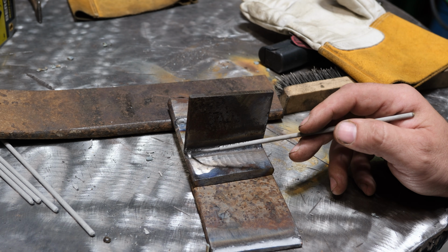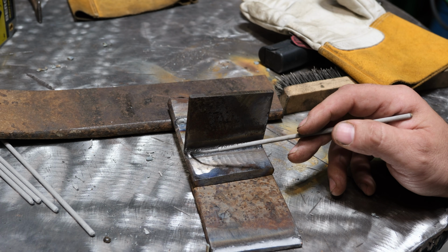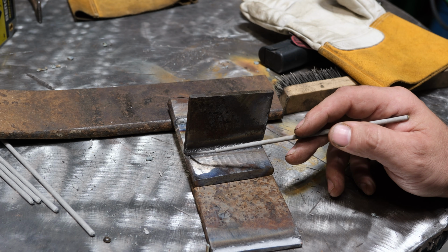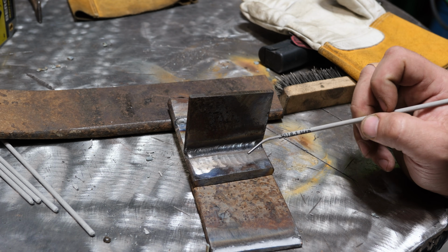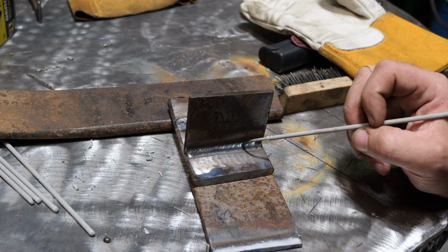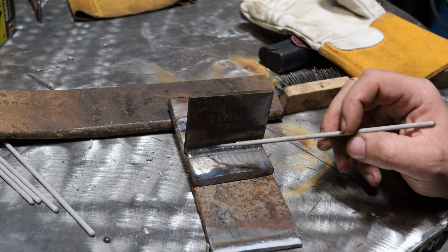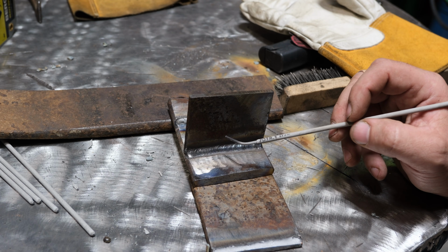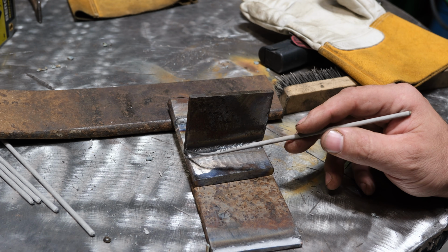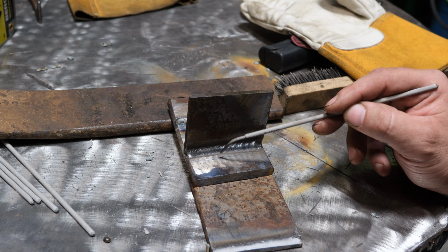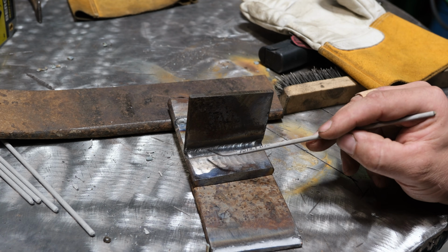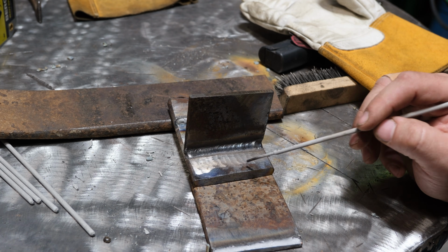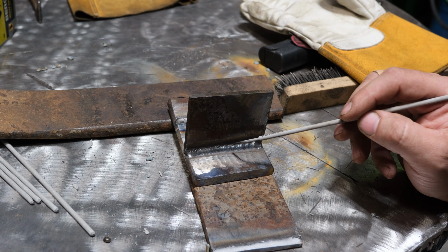Now, dull red is basically a faint red where you can barely see it in dim light. So you don't want this. If you can see it like cherry red or white or any of that, you've heated it far too hot and now you're in trouble. So we're going to be looking for a dull red. We want to see this base material, this upright plate, along with this weld, all roughly the same color.